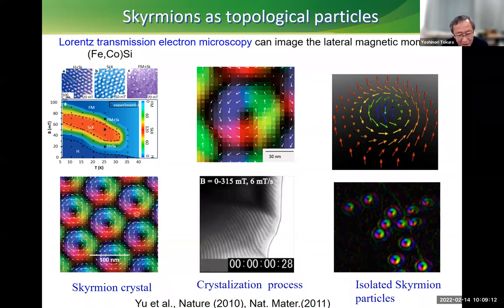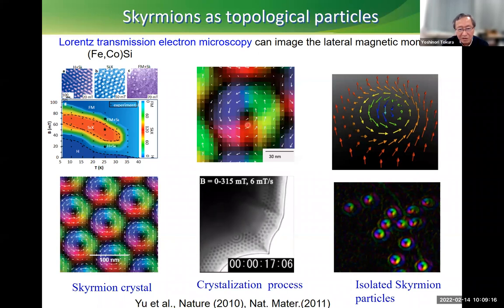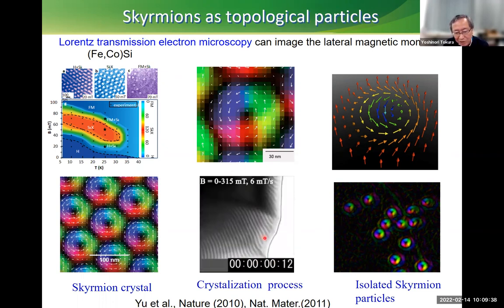But if you scrutinize this spin vortex, there is a black region where the spin moment is going up, and another region going down. In between, the spins show this rotation, a spin swirling habit. Originally the compound showed the helical structure, but if you apply the magnetic field, you can see some condensation of the skyrmion particles, forming crystals starting from here.